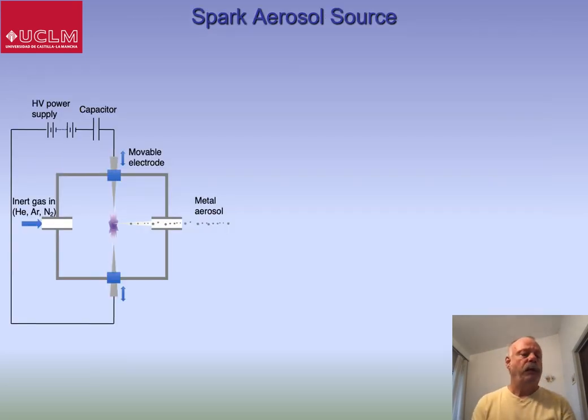Now, our silver nanoparticles were produced by a spark aerosol source. This is a simple device that initiates a spark between electrodes of the metal of interest, in our case, silver, and this spark is in the flow of an inert gas. We use nitrogen, and emerging from the source is a metal aerosol.